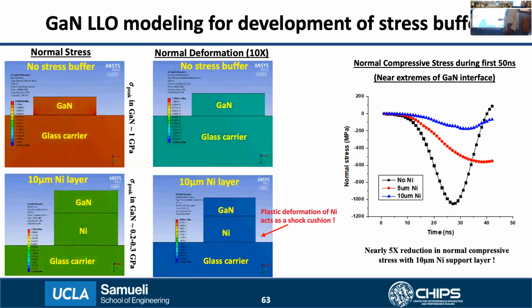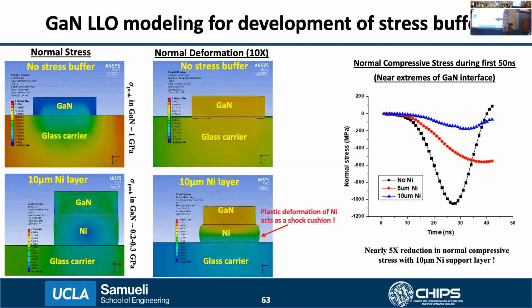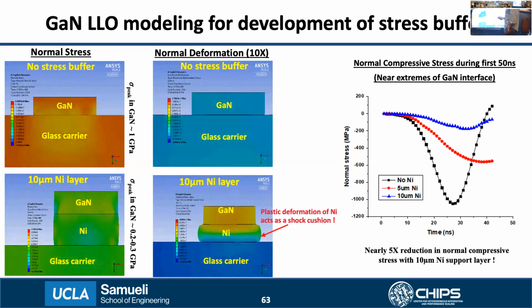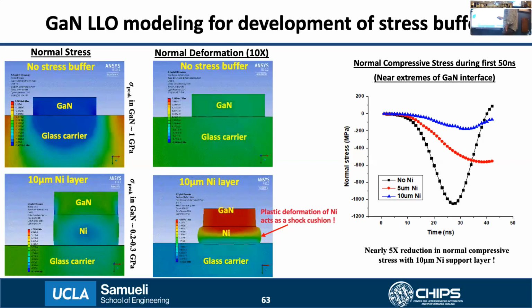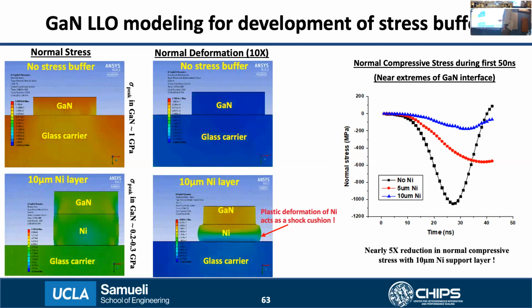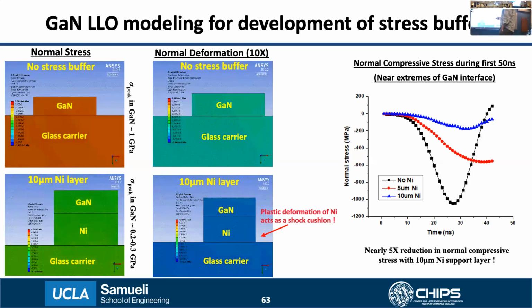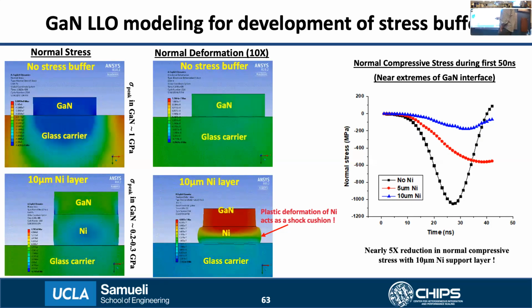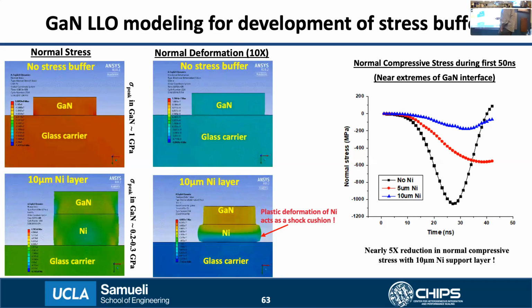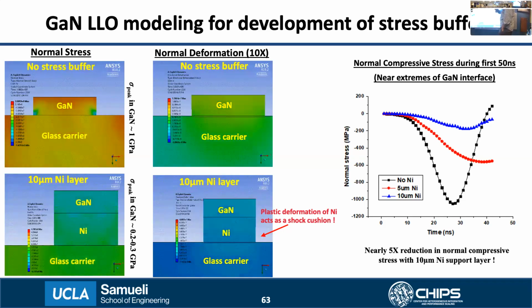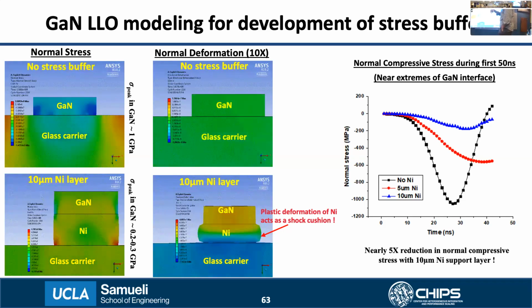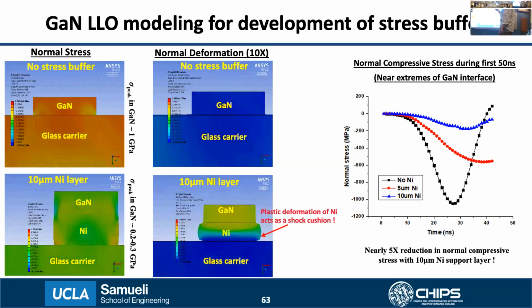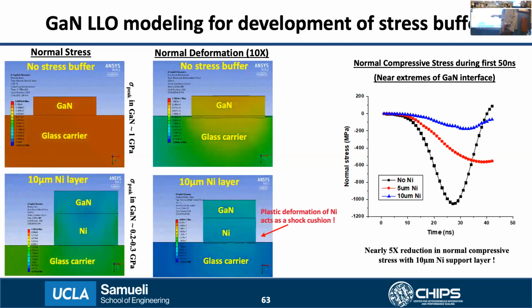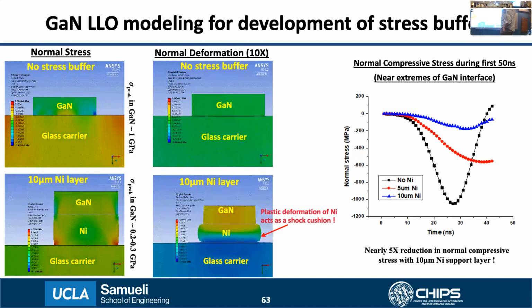Any questions? I'm curious, what boundary conditions did you use for the top side of the gallium nitride? The top side of the gallium nitride is where the pressure shock wave, the pressure pulse, is applied. That entire area is supplied with a constant pressure or force, which was calculated using the simplification. The bottom of the glass carrier is assumed to be fixed.